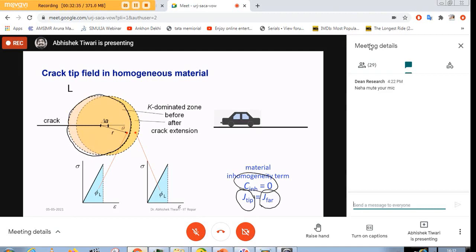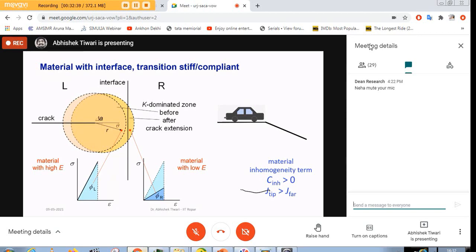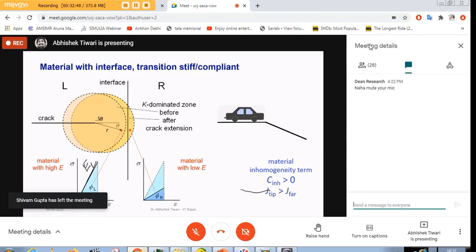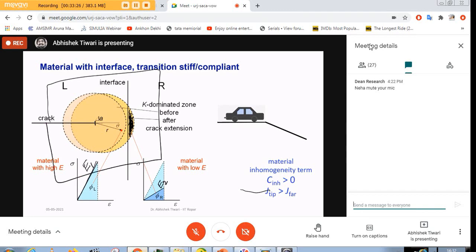But what happens when I have a transition of material? So on the left hand side of this black line, I have a material which has a higher Young's modulus, and on the right hand side I have a material which has a lower Young's modulus. And now let us take this contour. Initially I have no configurational forces except at the crack tip I get some value which is the crack driving force J tip. Then the crack grows and now my contour intersects with some of the part on the right hand side material. So what will happen in this side? In this side I will have less amount of energy because the elastic modulus is lower, so the area under the curve will be lower, and we are assuming elastic material only. So we will have lesser energy consumed here. Therefore, we have a bigger contour, and that is the amount of energy which we are providing, and the same amount of energy has to reach in this contour, but because less energy is consumed in this part, more energy is available on the other part.